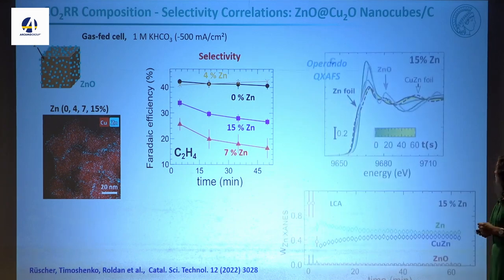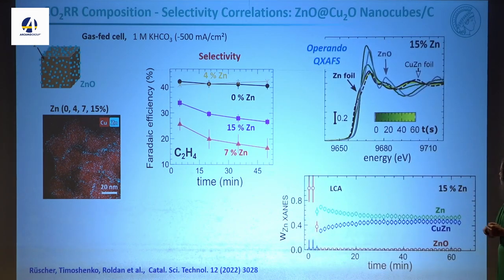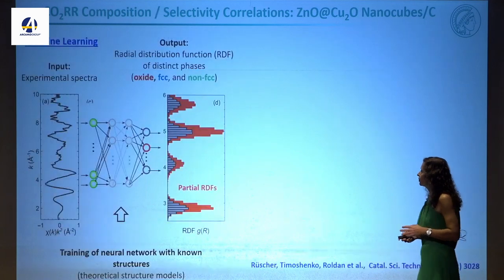So you can follow this now under reaction conditions with X-ray absorption spectroscopy. You can follow the zinc signal, and you can see that you are forming copper-zinc brass alloy under reaction conditions. And the realistic catalyst has a combination of zinc and this copper-zinc, and also some zinc oxide. I wanted to illustrate that we can do this very carefully.